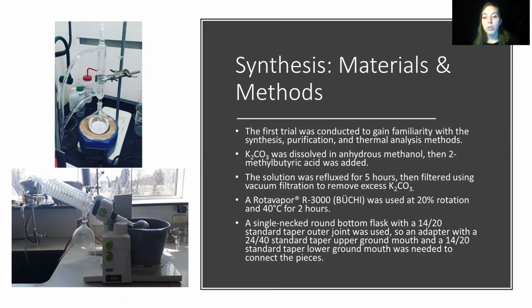A Rotavapor R3000, shown in the bottom left of the screen, was used at 20% rotation and 40 degrees Celsius for 2 hours. When this trial was conducted, the round bottom flask used had too small of a neck to fit onto the Rotavapor, so an adapter was necessary. Unfortunately, as the solution heated, it created pressure within the flask, which caused the flask to slip off of the adapter and pick up some water from the Rotavapor. This introduced a contaminant into the sample.